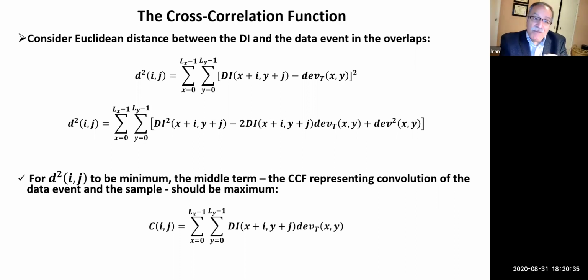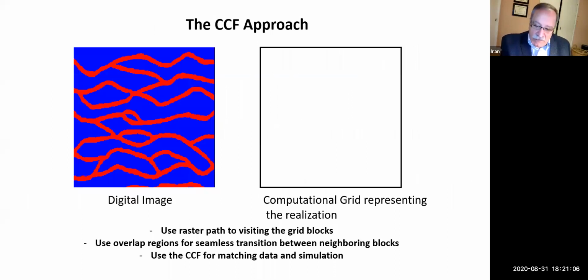But if you expand that, you will see that the first term on the right side and the last term on the right side are always positive, and therefore in order to minimize d squared, you have to maximize the middle term. And the middle term is basically a cross-correlation function or a convolution between your data and the sample that you have taken, which I have defined at the bottom. So you want to maximize that correlation function in order to minimize the difference between the data and what you have sampled. So that's basically the idea.